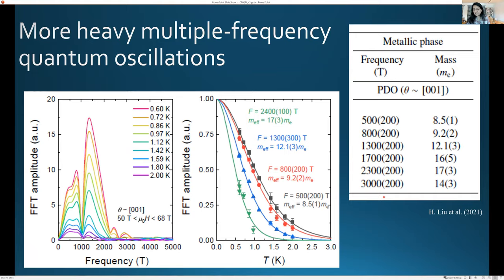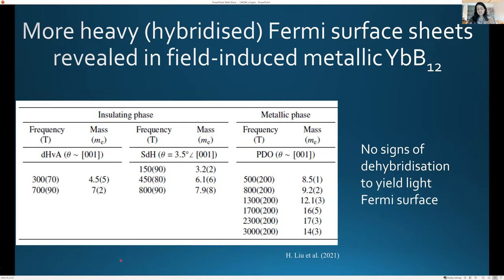So these are the metallic Fermi surface sheets from around 500 to about 3000 and masses from about 8 to about 14. And we can make a comparison of the insulating phase, which shows low frequencies and low masses. There's some overlap of these low frequencies and high masses, but it goes on to much higher frequencies and higher masses. So it could be just that the amplitude has grown and we're seeing more of the same Fermi surface. It seems to be that the Fermi surface is actually growing as we go to the metallic state.